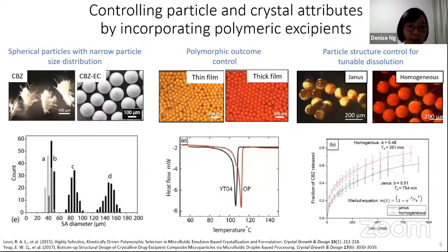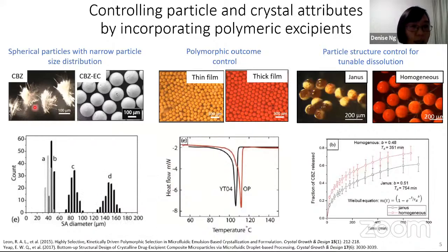However, it does not always crystallize into nice spherical agglomerates like we have seen for the case of glycine. For example, here I have the case of carbamazepine, where it crystallizes into bunches of needle-like crystals instead. It does not give that nice spherical geometry, which is preferred because it has better flowability properties as compared to the acicular crystals, and it is monodispersed in nature. Here we can incorporate a polymeric excipient. We have incorporated ethyl cellulose into it, and this helps to confine the crystals within a polymer matrix and results in the formation of monodispersed spherical agglomerates, spherical particles.